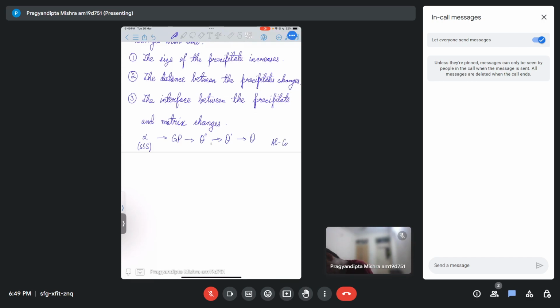Now this sequence is specific to Al-Cu. What we are seeing is specific to Al-Cu, but similar steps can also be seen for other precipitates. Sometimes you will not have all three stages, theta double prime, theta prime, and theta. Sometimes theta might not be the final state, it might not be the equilibrium precipitate. Sometimes in-between precipitates might also be in equilibrium, like theta prime along with theta. So there are different sequences, but in Al-Cu alloy systems, we will normally see this followed. This is generally seen, so that is what we will take as our learning process.